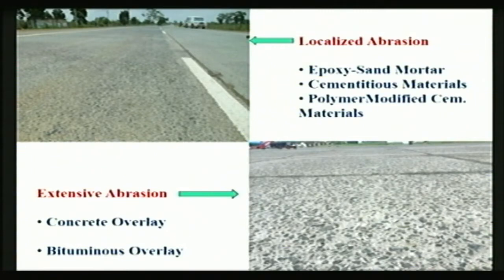This is the last. If your concrete is very poor, then after opening to traffic, you will see a very rough surface. The total texture has been removed from the surface. It is an indication that your concrete is not of M40 grade. And definitely it is less than M25 grade, because concrete up to M25 or M30 grade may take some traffic without removing the texturing for some time.